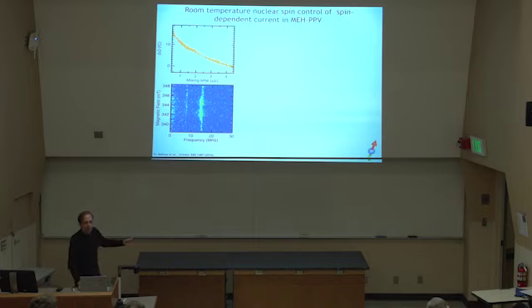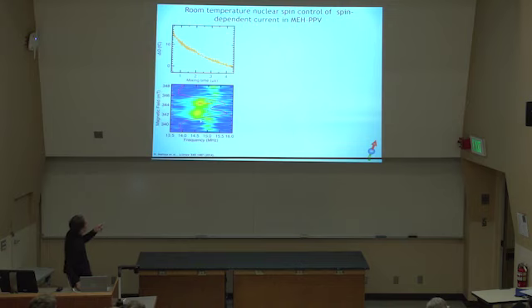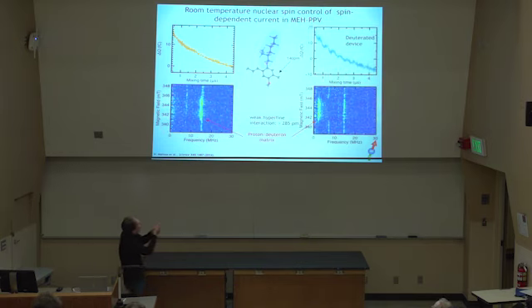Just because the numbers fit here, that's not a proof, of course. So we did what I already introduced earlier. Yeah, you can zoom in here, so it's around 14.5. However, note, it's hard to see here. You see already this frequency around 14.5 seems, it's not significant because of the width and the fuzziness of these features. Shifted a little bit to lower frequencies and lower magnetic fields. So that's kind of consistent, but no proof, of course. So what you do is you repeat the same experiment with the same polymer, but you replace your hydrogen by deuterium, and then you repeat it, and all of a sudden your oscillation has a low frequency, and all of a sudden this signal is mostly shifted here to a frequency that's 6 times smaller, not completely, because some hydrogen were actually left here. This was not completely deuterated.